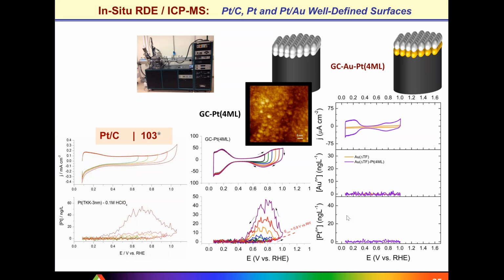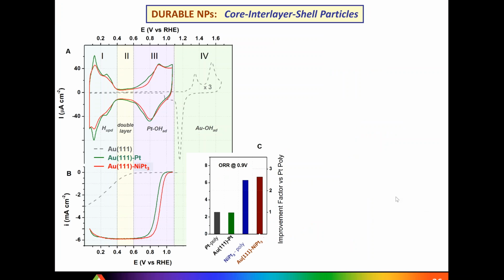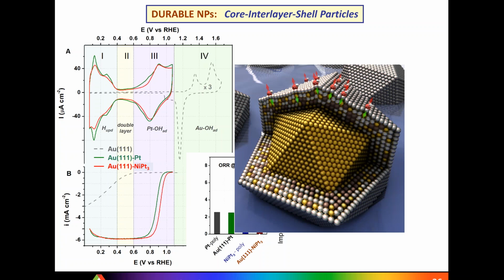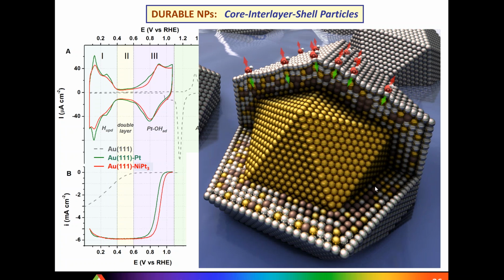So again, this is an extremely important design rule, which was immediately applied to several of those so-called core interlayer shell type of particles, and due to the extremely high onset of formation of surface oxides, gold is much less oxophilic than platinum, as one can see from those voltammograms on this slide. Gold in background versus platinum type of surfaces. And here is how our core shell particle looks like. Gold in subsurface coated with at least 5 platinum-based